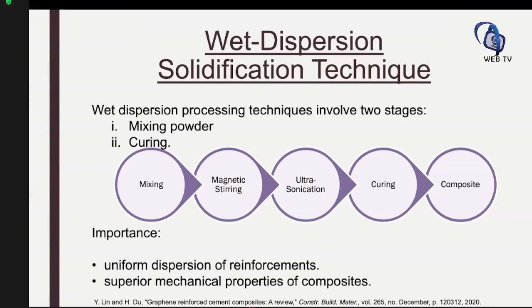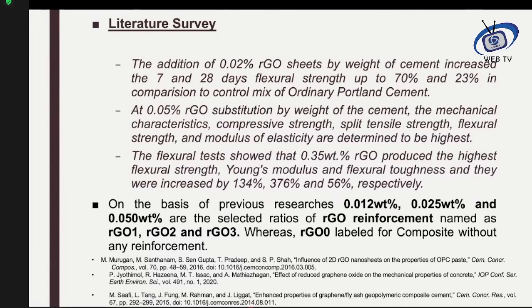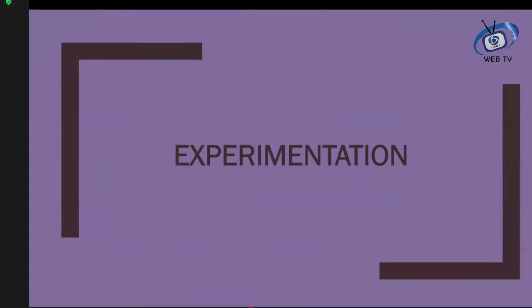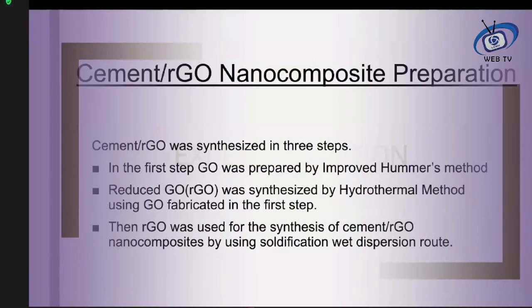The process used for the cement and RGO fabrication was the wet method, in which the powder was mixed along with RGO and some curing was done. Curing is the process in which the cement is usually left to stay and sprayed or sprinkled with water to settle down and reduce the loss of moisture from the cement. The previous literature survey tells us that RGO is very well used as a nano reinforcement for adding additional properties to the material structure. Different ratios of RGO can be added for the cement nanocomposites.